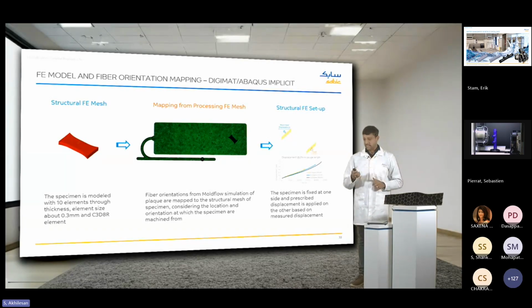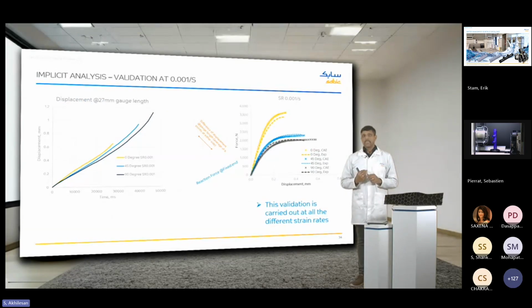Then we apply the structural boundary conditions. Now, in the structural boundary conditions, there are two things we do. One, we constrain one side of the specimen, and on the other side, we apply prescribed displacement. And this prescribed displacement is similar to the way we perform the test.